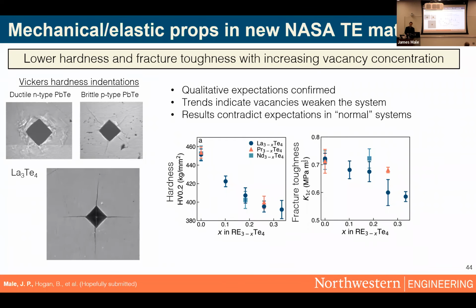Now, turning to mechanical properties, we get some pretty interesting results. So I used, again, these Vickers hardness tests, similar to what I did in lead telluride. And I found that the hardness decreases with increasing vacancy concentration. And also the fracture toughness decreases quite a bit. So to briefly touch on fracture toughness, this is essentially a measure of how easily a crack can open through a material. And I was actually able to measure this in lanthanum telluride because it has this nice ceramic type cracking behavior at the indentation tips of my Vickers indents. You can actually measure these crack lengths to get an estimation of fracture toughness. But basically, reduced fracture toughness means the thing cracks and breaks far more easily. So clearly, our results are pretty much confirming what we believed qualitatively, but have never actually measured, which is that they get more brittle with vacancies.